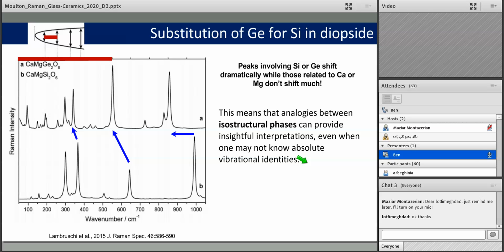We mentioned a moment ago that there is a mass effect, and if we have a larger mass, we should decrease the frequency. And this is exactly what you see here. These are two crystals, calcium magnesium germanate and a calcium magnesium silicate. And they are isostructural. We see that in the silicate on the bottom here, the frequencies are shifted here by about 100 wave numbers, here by a little bit more than that. And we see a smaller shift, but still a shift nonetheless, in these peaks down below.